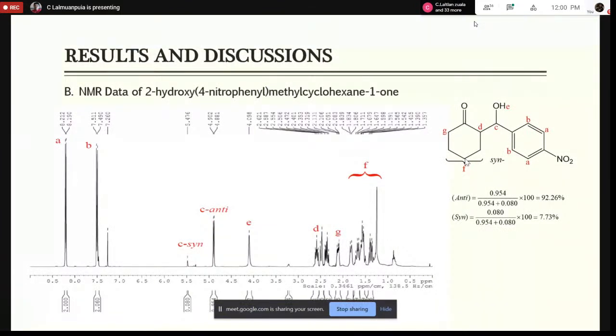Now let us look at the proton NMR spectra of para-nitrobenzaldehyde with cyclohexanone as an aldol donor. The chemical shift at 4.9 ppm, this one, corresponds to the proton C in the anti-diastereomer, while the 5.4 ppm corresponds to proton C of the syn diastereomer. The peak integrals of the syn and anti-diastereomer suggest that the diastereomeric ratio of anti to syn is approximately 92:8 in favor of the anti-isomer. This infers that the OPA catalyst does not simply catalyze, but offers a high diastereoselectivity as well.